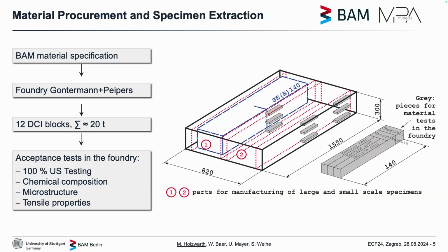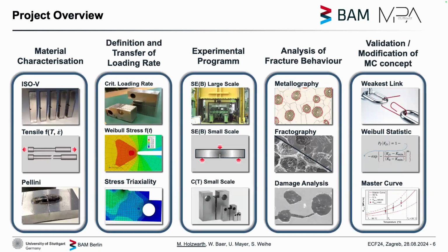And further, after the testing of the SEB 140, we have extracted more specimens from those broken halves of those specimens, mostly the smaller SEBs and CT specimens. This slide we all have already seen. On our side at MPA Stuttgart, we are mainly doing the Pellini testing and the CT testing. The Pellini testing is already done. My colleague already mentioned it.